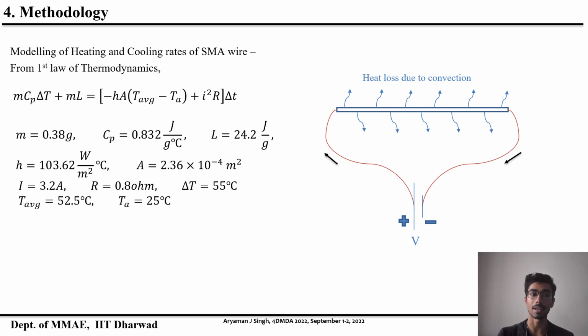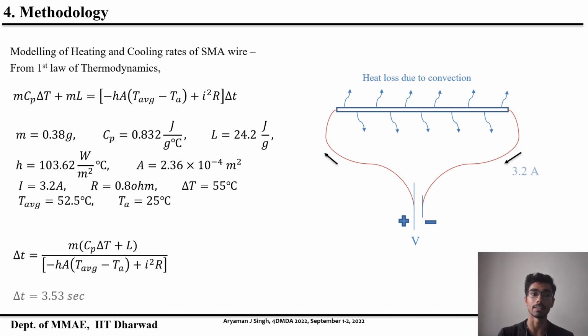These are the parameter values we used to calculate the total time required to heat the SMA wire from ambient temperature to its austenitic finish temperature at 80 degrees Celsius. It is obtained as 3.53 seconds.